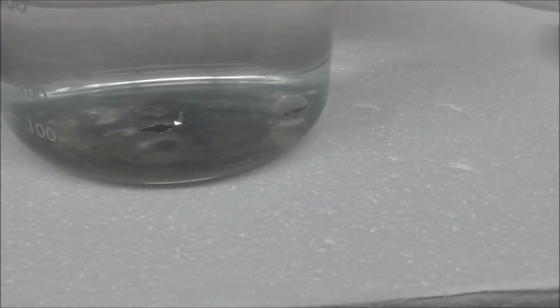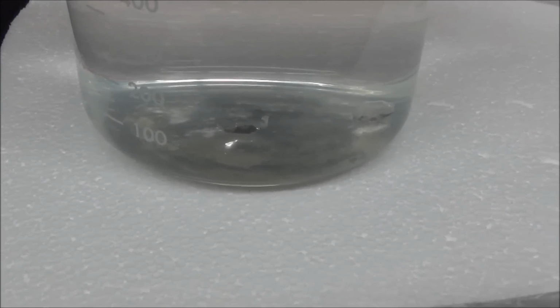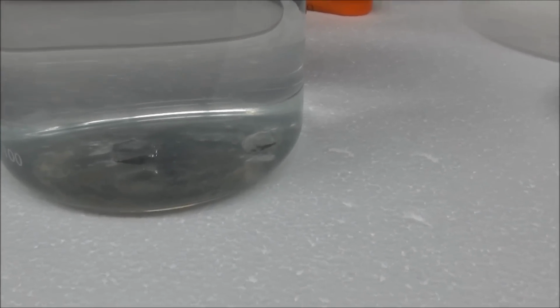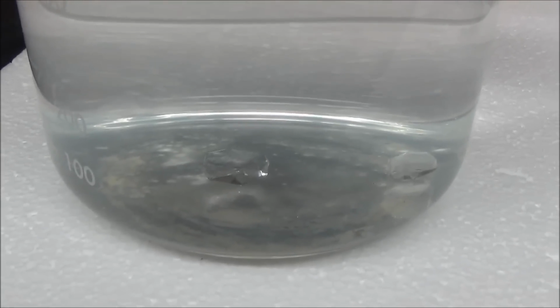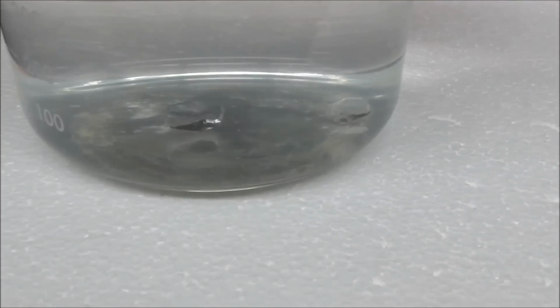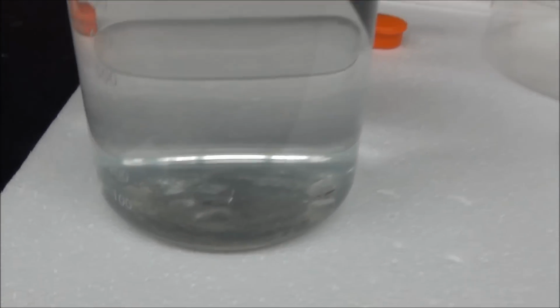Now the good news is overnight those crystals definitely started growing. So they have increased in size. The problem is there are new crystals forming at the bottom of this beaker, and ultimately what we really want is a good single crystal, and if we have small crystals clumping together, it's not going to be a good single crystal. So we're going to have to fish those out, and instead of super gluing it this time, I think I'm going to try tying the string to the crystal.